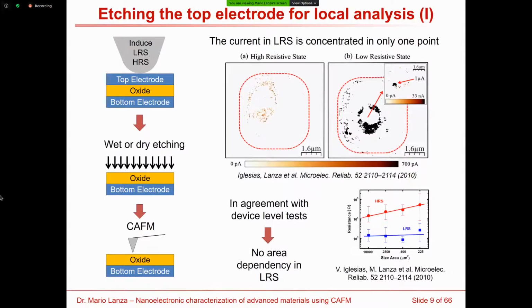For example, imagine that you have a real electronic device that is based on a top electrode, an oxide, and a bottom electrode. And you apply some electrical stresses at the probe station. And after that, you want to analyze the sample. You want to see where these defects are formed and where the conductive filaments are formed. So basically, one option that you have is to etch the top electrode with one chemical method and then use the tip of the conductive AFM to scan the surface of the sample. If you do this, you can obtain something as you can see here in these A and B panels.